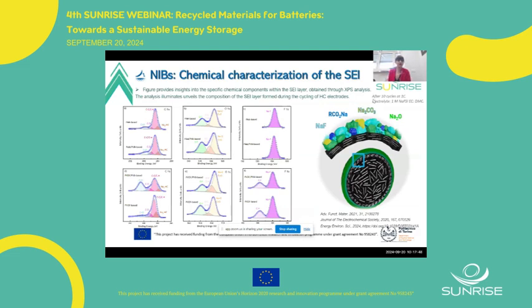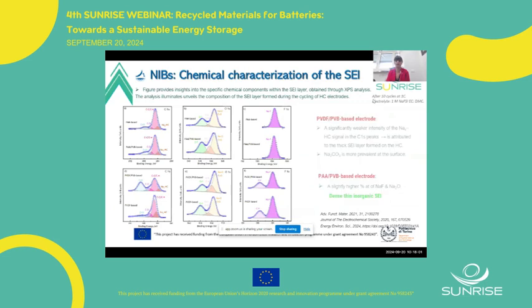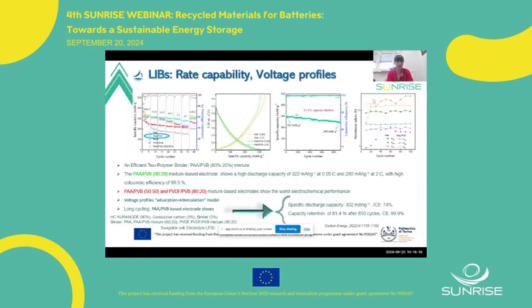In order to analyze the SEI, the passivation layer of all electrodes after cycling, we washed the electrodes and made some XPS measurements. We understood that the PAA-PVB based electrode has a dense and thin SEI, while the PVDF-PVB based electrode has a thicker SEI, which is why it shows worse electrochemical performance.